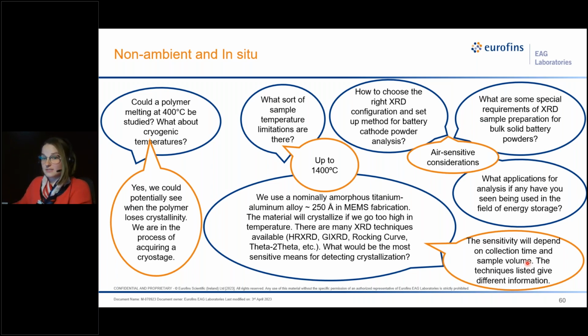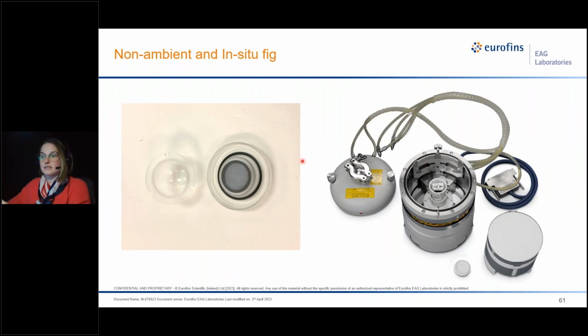We have a glove box for air sensitive samples. So this is a typical air sensitive sample holder. You would essentially pack your sample in the glove box. There's a sealed O-ring here, and this is just a plastic dome, and the X-rays go through it. It's going to give you an amorphous background, but we know the background of the sample holder, so we can subtract that out. And then this is our HT 1500 high temp attachment for our Rigaku SmartLab. As it's named, you can go up to 1500 degrees C, and you can use it with any kind of atmosphere: nitrogen, argon. You can run any kind of gas you want through the oven itself.